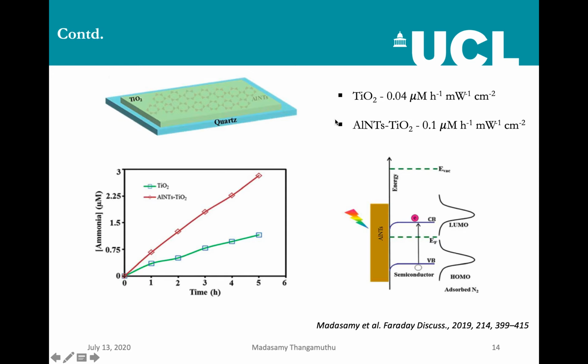As you can see, the green curve, the ammonia produced using just titanium dioxide semiconductor is just 0.04 micromolar per hour per milliwatt power per centimeter square, because of the surface area we have to mention. Once we embedded the aluminum nanotriangles, you see it's more than 2.5 times enhancement. So 0.1 micromolar per hour. You can see in the graph, it's the red line. This is after aluminum nanotriangles were embedded.